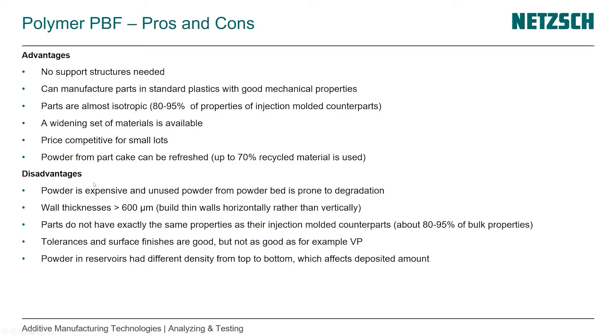However, disadvantages are that the powder is expensive and the unused powder is prone to degradation. That's why we're not using all of it, we're doing the refreshing. Wall thicknesses of bigger than 300 micrometers are possible.